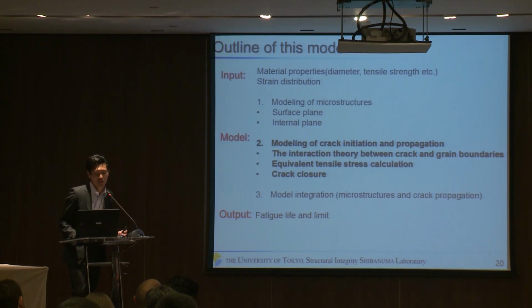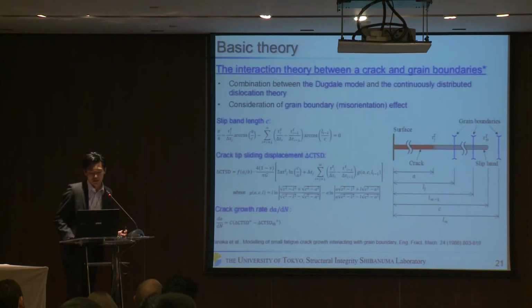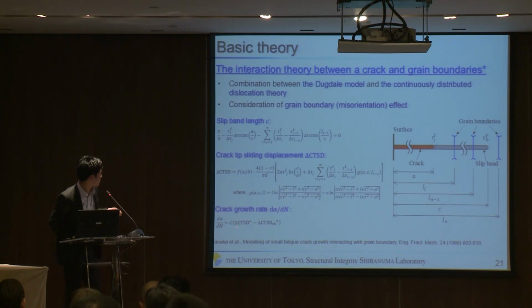The next topic is modeling of crack initiation and propagation. This model is based on the interaction theory between the crack and the grain boundaries, also known as the Tanaka-Mura model, proposed by Tanaka et al. This is a combination of the Dugdale model and the continuously distributed dislocation theory. Slip band length and crack tip sliding displacement are calculated from these equations. Based on this model, the effect of a grain boundary can be considered. And the crack growth rate is shown in this equation. This is called Paris law, and this is the CTSD threshold, which means crack arrestability.